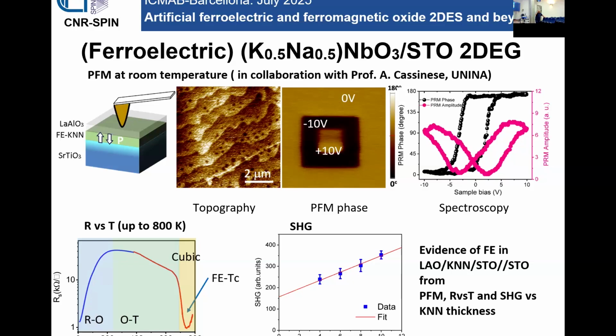For sure, for example, oxygen vacancies in lanthanum aluminate in particular play a role. And what I can tell you is that we have done another experiment I didn't show, which was the time dependence of the amplitude of the PFM signal. This is a classical method to understand if you have just charging. For example, you can have just localized charge that you write, or there is ferroelectricity, and over 4 days the change of amplitude was 20%. So in our opinion this behavior is that of a ferroelectric. But that alone is not enough, and this is the reason why we performed these other experiments and also the second harmonic. Then maybe we'll try the ferroelectric test analyzer. This we'll try, but I'm not sure it will work. Maybe more simply, considering the physics of the two-dimensional gases, it's simply impossible to switch completely a ferroelectric layer, no?